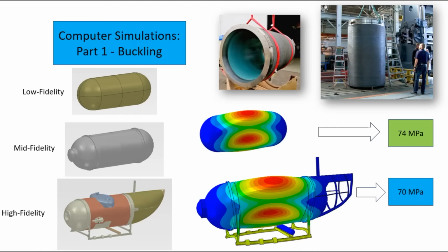In the simulations, three main aspects are considered. The first aspect is buckling. The linear buckling analysis results in a design pressure of about 70 megapascals, depending on the order of fidelity.